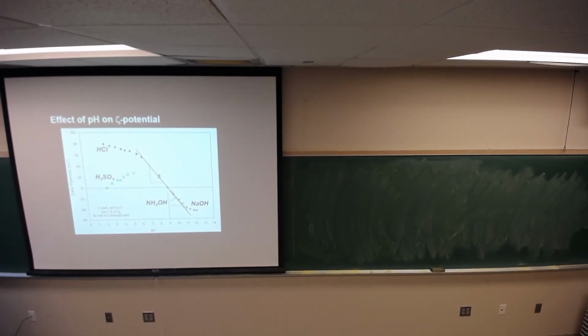What's the charge on the particle surface? This is not a guess, right? You don't have to guess. Because you have, this is positive, this is negative, so the particle surface is positive. So you bring in a divalent sulfate ion that is a divalent counter ion to that surface charge. So what's happening is that the sulfate ion concentration is sufficient to compress the double layer.